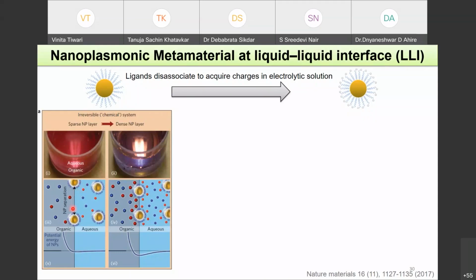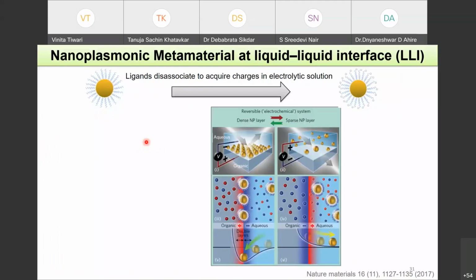If the separation is large, they behave like a weak mirror. You see there is a candle holder which we put next to it, and you see a weak reflection. But when there are more nanoparticles in this interface, the interface becomes like a strong mirror and you see a very strong reflection. Now, what is the problem in that system?